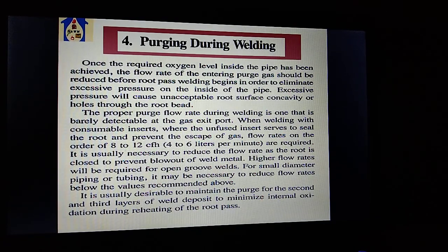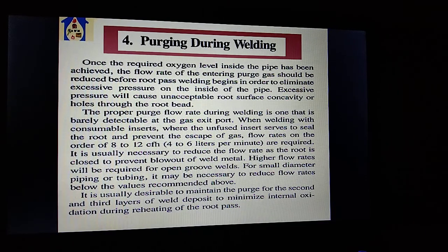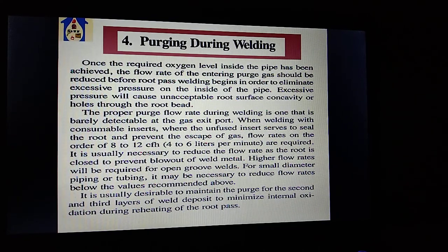Purging during welding. Once the required oxygen level inside the pipe has been achieved, the flow rate of the entering purge gas should be reduced before root pass welding, in order to eliminate excessive pressure on the inside of the pipe. Excessive pressure will cause unacceptable root surface concavity or a hole through the root bead. The proper purge flow rate during welding is one barely detectable at the gas exit.